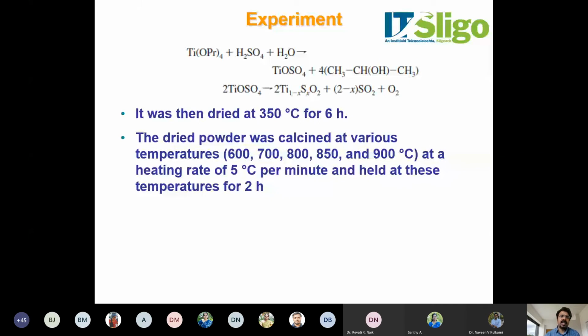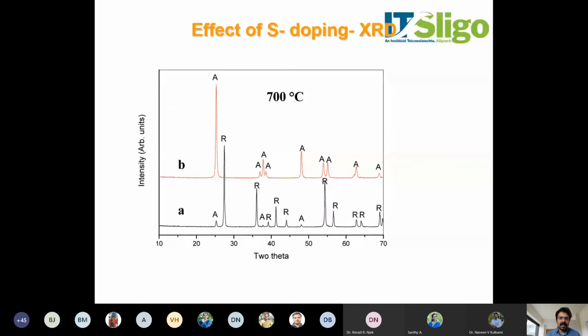Pradeepan used very simple technology. Pradeepan used titanium isopropoxide and used sulfuric acid as a kind of stabilizing agent, and then treated this isopropoxide with sulfuric acid, and then a range of different types of precursors are formed, and it was stable up to 350 degrees Celsius, and no crystalline materials are formed, but the dried powder calcined at various temperatures. We can see that the anatase is stabilized, or no rutile is formed up to 700 degrees Celsius. But if you look into normal TiO2 without adding sulfur, rutile is formed even at a temperature of 700 degrees Celsius.